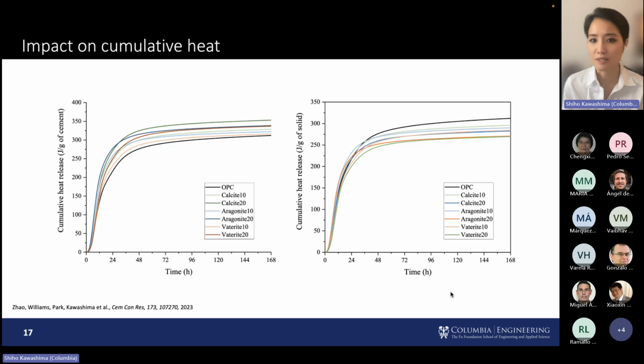But ultimately, we're interested in what the impact is on mechanical properties, specifically compressive strength. And so if we want to start getting an indication of that, we normalize with respect to total solids. Up until now, I've been reporting the results for hydration kinetics and cumulative heat release with respect to mass of cement. But now we're going to do mass of solids, and the cumulative heat release there will be an indication of mechanical strength. And once we do that, we see that ultimately OPC does exhibit the highest cumulative heat release. And that is because calcium carbonate is going to be a less reactive material compared to OPC, so there's going to be that dilution effect.